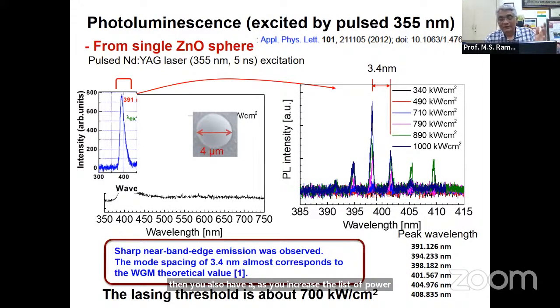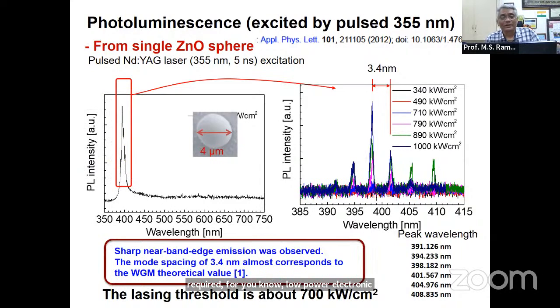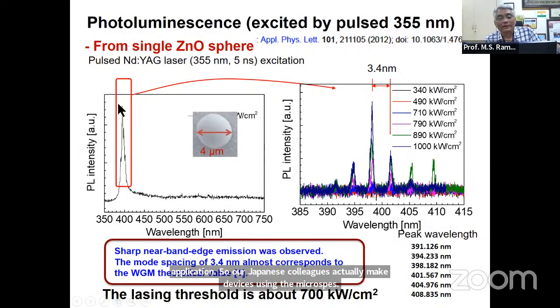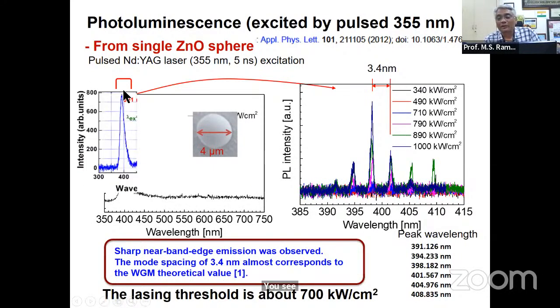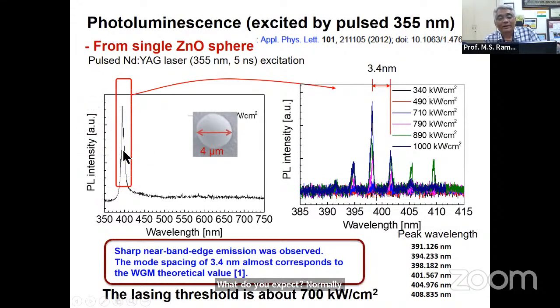These are required for low power electronic applications, so our Japanese colleagues actually make devices using the microspheres. A smooth transition that you'd normally expect in bulk or thin film zinc oxide transforms into these spiky structures, and when you expand this is what you get. The lasing action happens at a very high threshold.